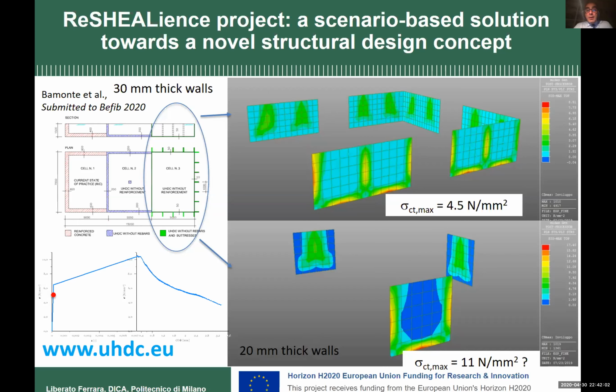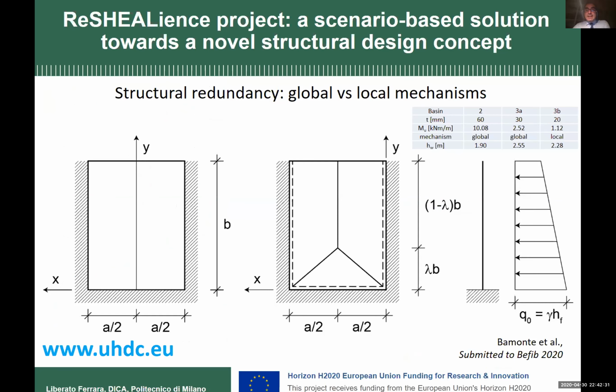Obviously the stress increases because you go to 4.5 and even to 11, and 11 is outside the material capacity. But first of all, it's very localized at the borders, at the boundaries of the slab. The other thing is that this is an elastic analysis, and we know this material really works in the post-elastic regime. This calculation, to which Salam Al-Obaidi also participated with Professor Bamonte, has been submitted as a paper to a conference in September.